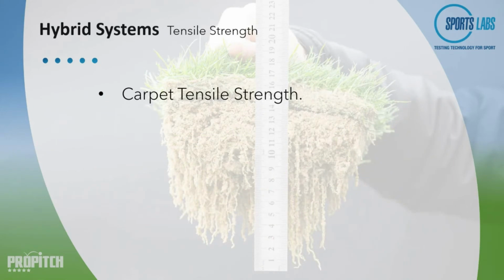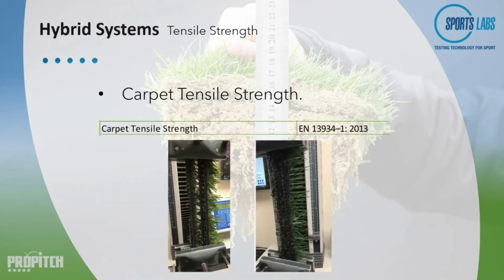Next, we can look at the tensile strength and elongation of the hybrid system. This is carried out in accordance with EN 13934 Part 1. The testing itself consists of cutting out test specimens from the hybrid carpet 50mm wide and at least 250mm in length. These are conditioned in the laboratory prior to testing, and then they're placed in the tensile machine as shown here in the pictures. They're then pulled apart to determine the maximum force and elongation.